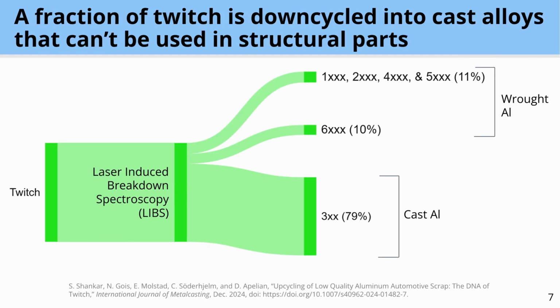So this Twitch is then broken down using LIBS, which is laser-induced breakdown spectroscopy, into the wrought portion and the cast portion of the alloy. The wrought portion, which makes up about 20% of the Twitch, is usually sold back to companies like Hydro, where they will then put it back into their products and reuse it. While the cast portion, which makes up about 80%, is usually downcycled into lower value alloys. Our project focuses on finding a use and enhancing these cast portions of Twitch into higher value alloys.